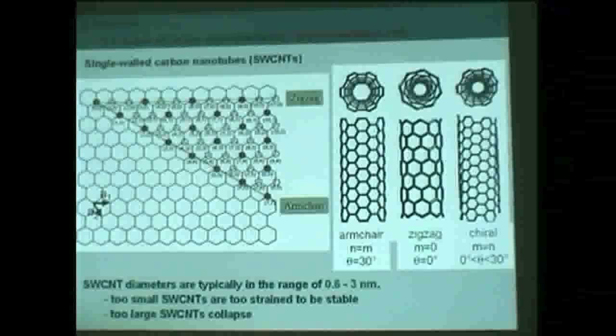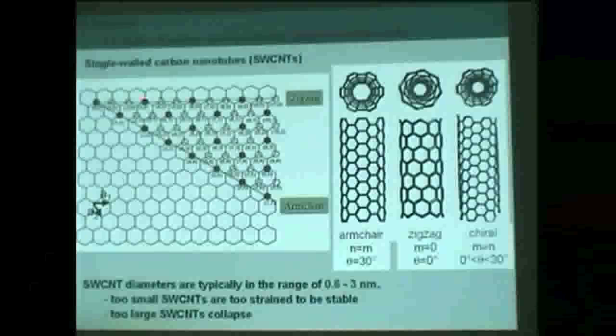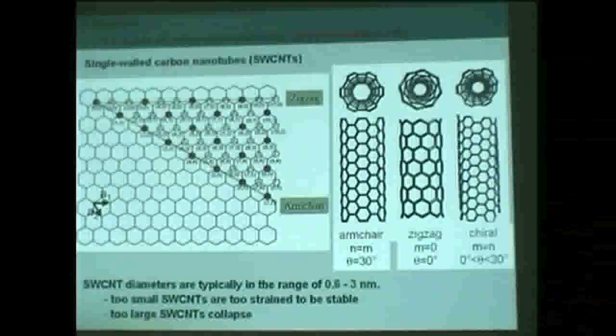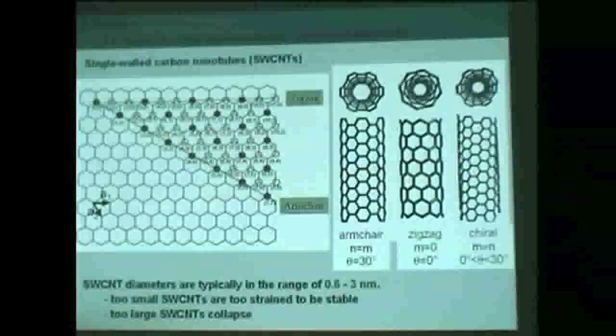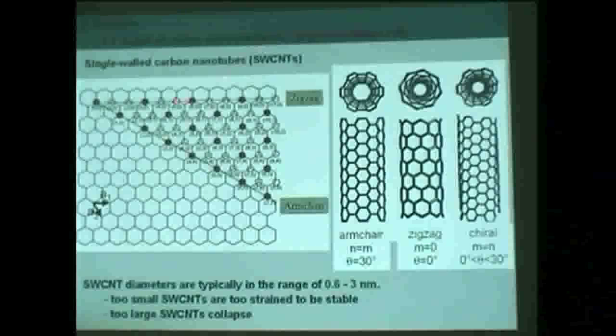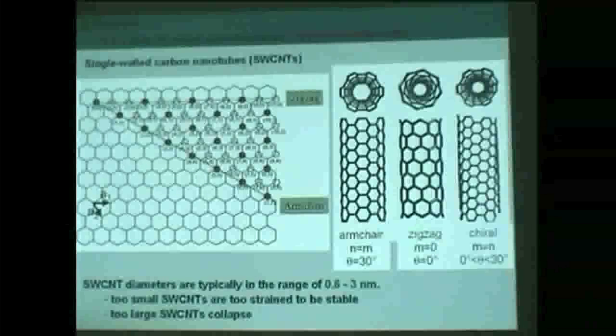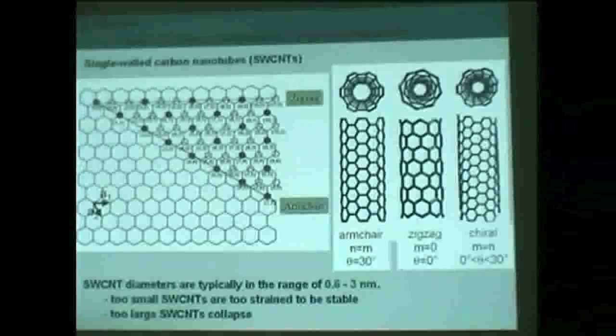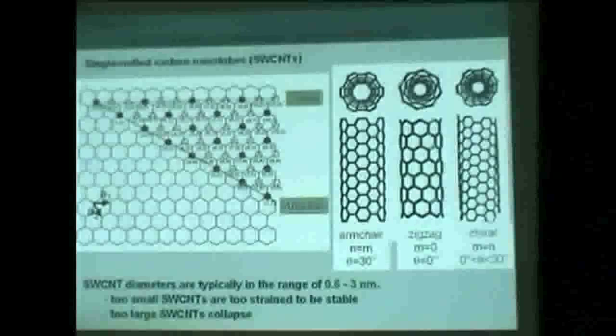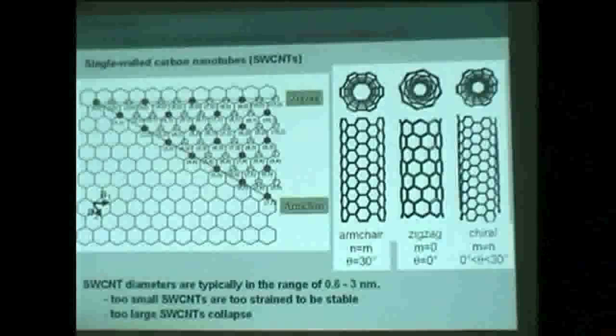What is the difference between the red spots and the white spots? It's the electronic properties which are different. The red one corresponds to tubes which are metallic, meaning very good electrical conductors, like copper. On the contrary, if you end up on a white point, you'll have something semi-conducting, like silicon. So the electrical and optical properties are completely different depending on how you roll up the graphene sheet.